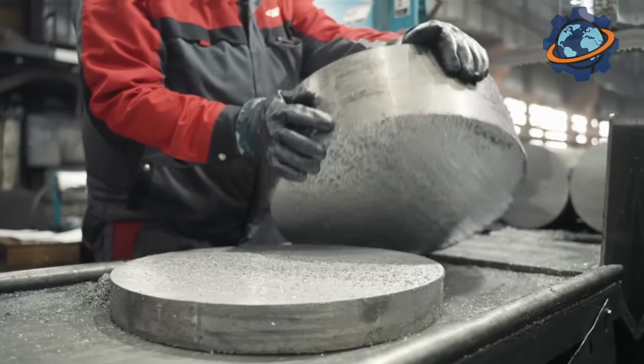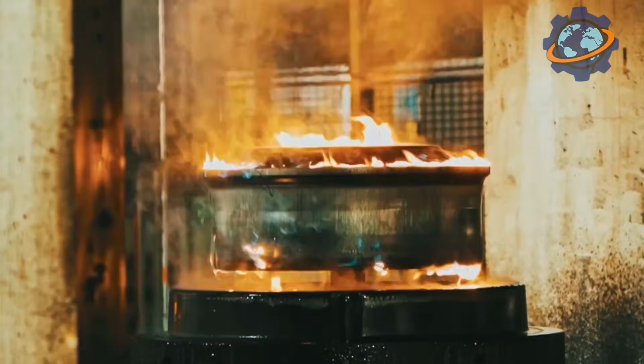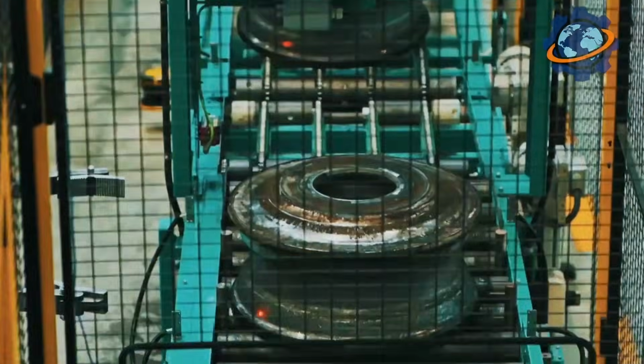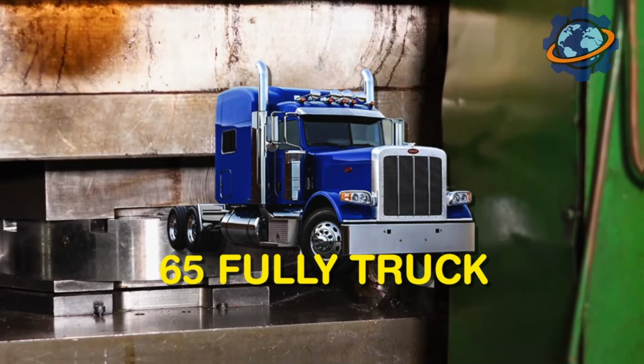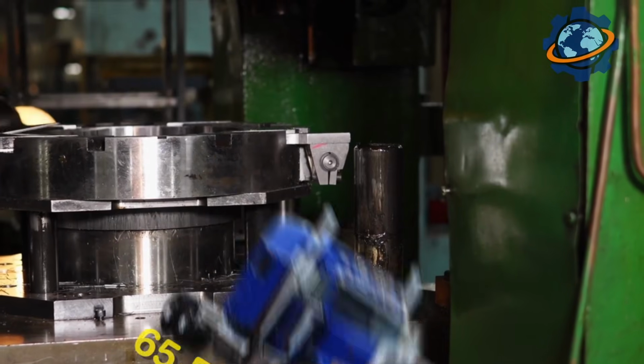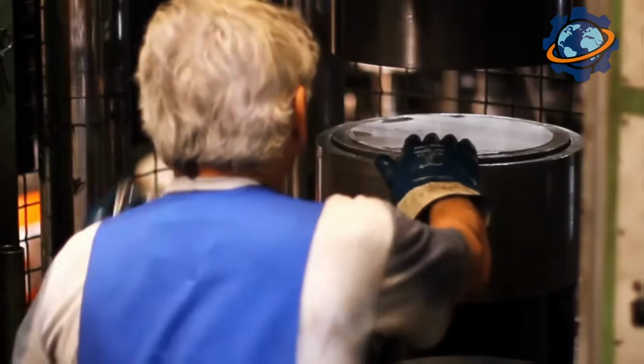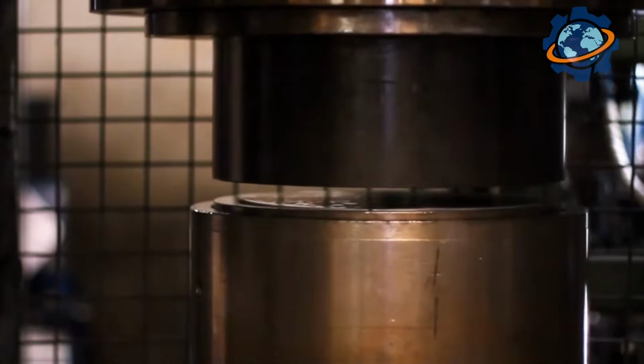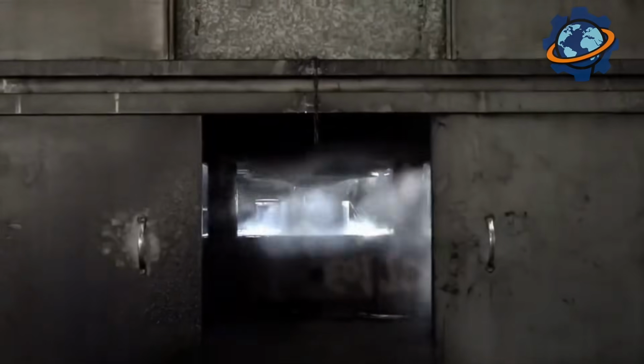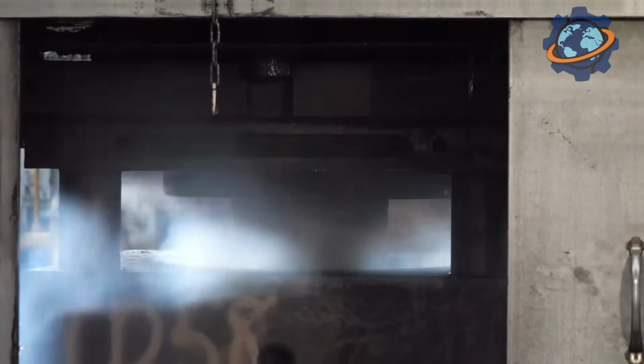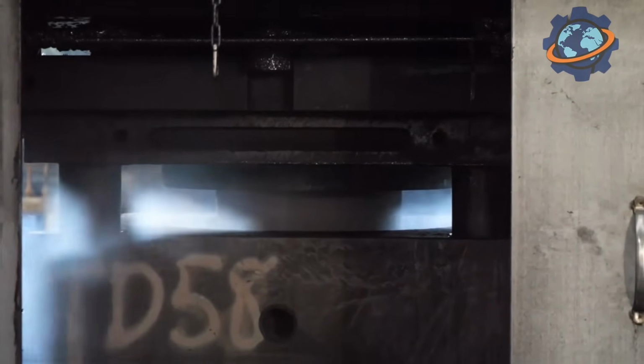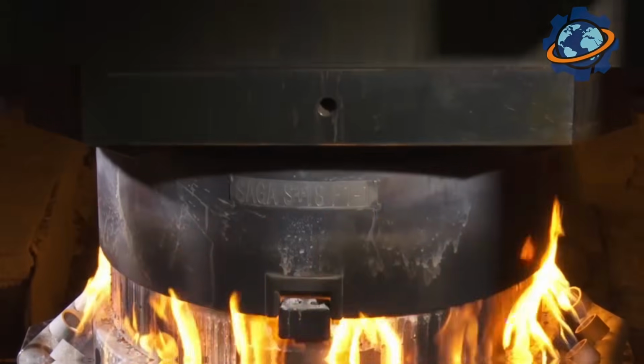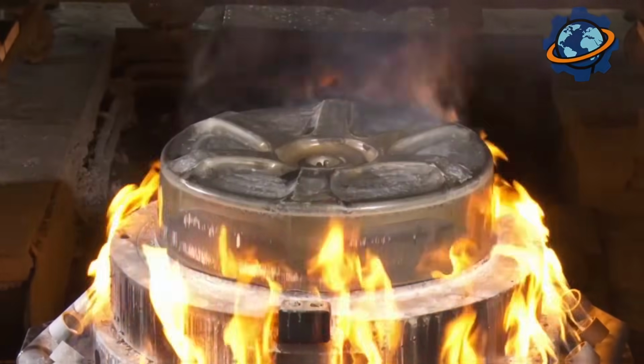And now it hits the press, a hydraulic press with 8,000 tons of force. That's roughly the weight of 65 fully loaded semi-trucks stacked on top of each other. All that force concentrates on a single billet 12 inches in diameter. The press descends, it takes a fraction of a second. The glowing hot billet that just looked like a cylinder spreads into a disc in one blow. The metal literally explodes outward, filling the mold. Sparks of scale and steam fly from under the press.